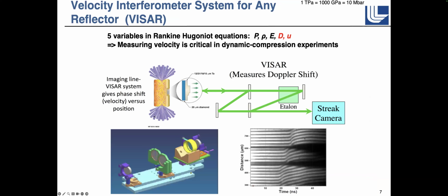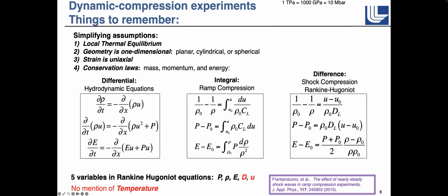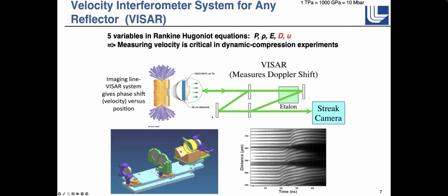We use a velocity interferometer system for any reflector, called a VISAR, to measure these velocities, because two important ones, shown in red, are the shock velocity and the particle velocity, which we can measure using a VISAR. It's essentially an interferometer where we bounce a laser off of our sample and look at the reflected light, and we have a non-equal path interferometer here, and we tune it so that we see fringes. As the frequency of the reflected light changes due to the Doppler shift, we see a change in the phase of the light transmitted through this interferometer, and that shows up as motion of these fringes. The amount that these fringes shift is proportional to the velocity that you're measuring.